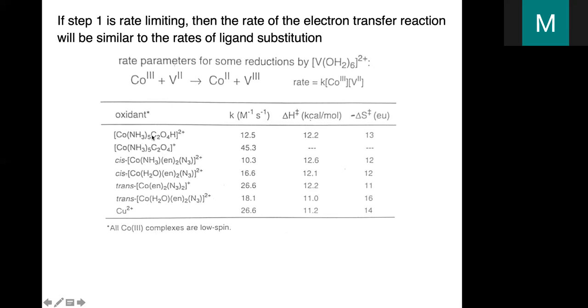ligand. So this is protonated oxalate. This is oxalate. This is azide, N3 overall 1 minus. These all have azide. And those cobalt-3 complexes are being reduced here by vanadium-2 and giving then vanadium-3 and cobalt-2 products. And so here you see measured rate constants under similar conditions for all of those reactions, and they're very, very similar. This is what you would expect for a case where step 1 is rate limiting.